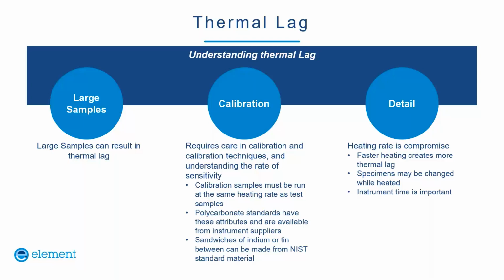thermal lag, generally the heating rate in a DMA experiment is a compromise. Slow heating minimizes the thermal lag. So if you heat very slowly, the center can come to the temperature of the outside as you're going along. Faster heating creates more thermal lag and errors related to thermal lag, but because specimens can be changing while they're heated, sometimes that's what we do. Specimens can be curing or drying, and so fast heating eliminates the effects of that and allows you to just measure the glass transition temperature of the material without that curing or drying. And of course, instrument time is important. People want to be able to run more than one DMA experiment each day.